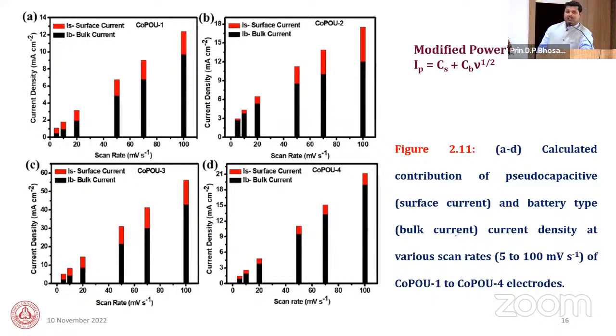Then I calculated the contribution of battery type and pseudo capacitive type behavior using this modified power law method. In this study, we can see the battery type behavior is increased as compared to capacitive behavior. It means our material is more battery type as compared to pseudo capacitive material.